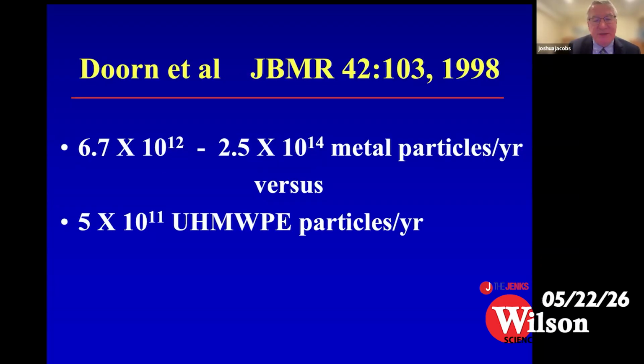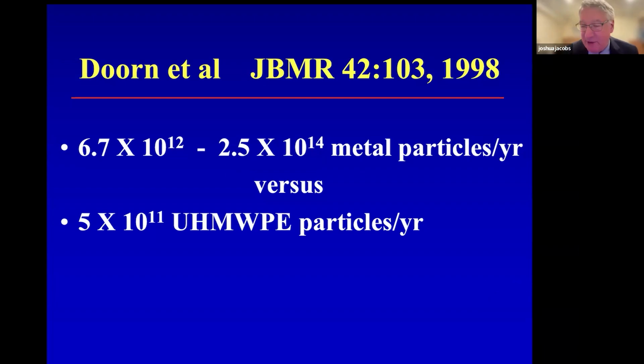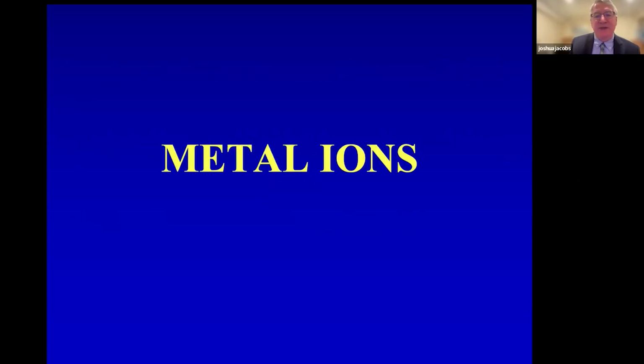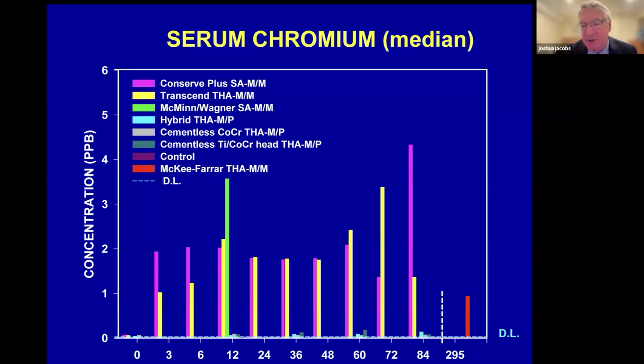Now, one of the consequences of this very large number of very fine particles, less than 50 nanometers, is that there's an enormous specific surface area, defined as the surface area divided by weight. And the reason the surface is important is that it's on the surface of the particle that there's interaction with the local environment, either the periprosthetic fluids or the cells. And the greater the surface area, the greater the interaction with the environment. So one of the consequences of this very large specific surface area is that you can measure metal ions or metal debris, it could be nanoparticulates, they could be ions, not only in the synovial fluid, but also in the serum of patients.